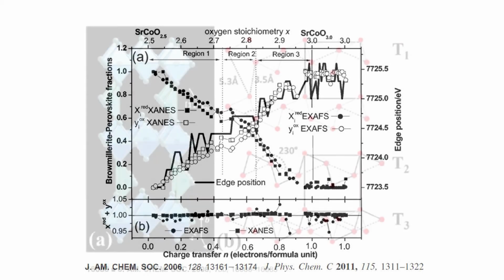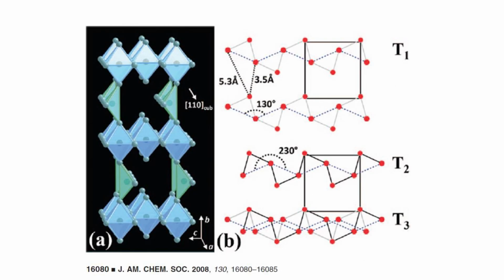And now we have to try to understand how it is possible, how does oxygen penetrate and migrate into the crystal. This is a nice picture, but it is a simple picture that shows you again octahedral, tetrahedral, octahedral, tetrahedral layers. In this case, you see that these tetrahedra are perfectly ordered. In this layer, all tetrahedra look in this direction, okay? This is an oversimplified version.